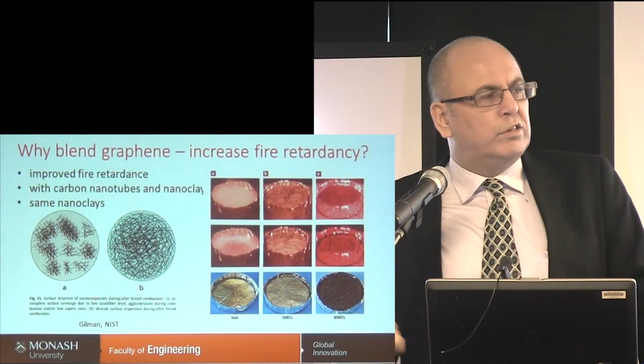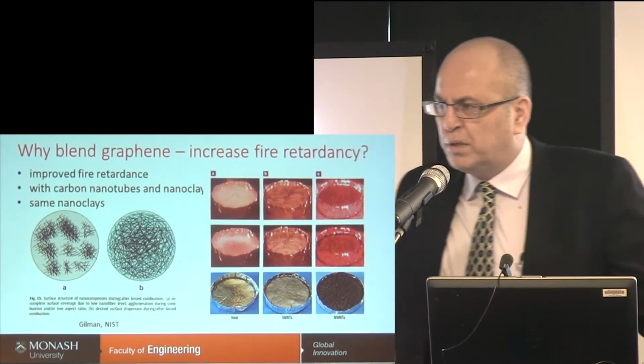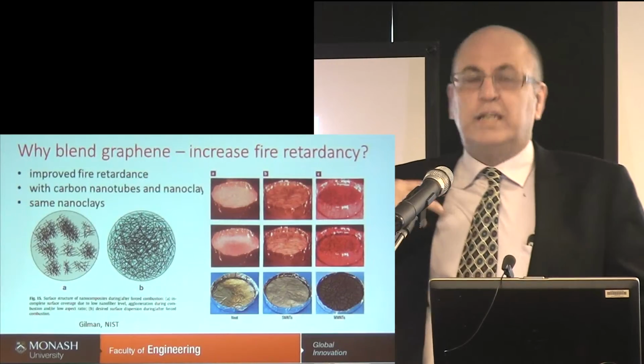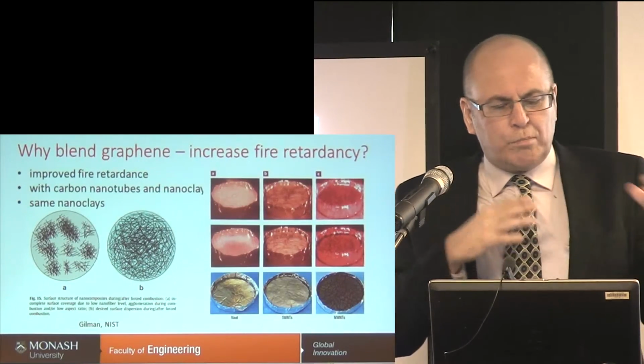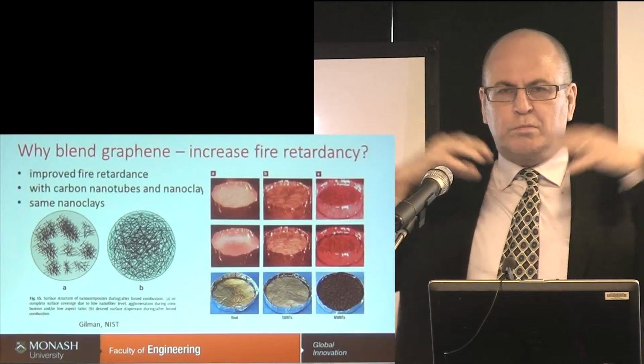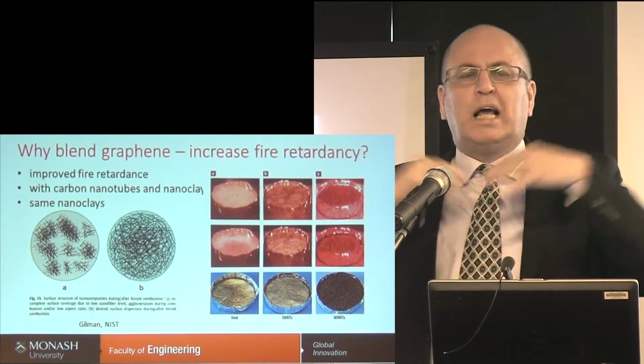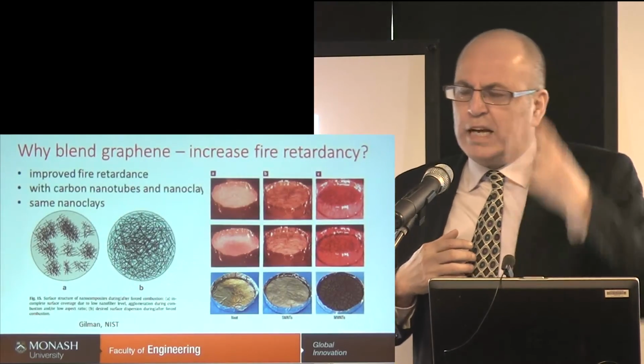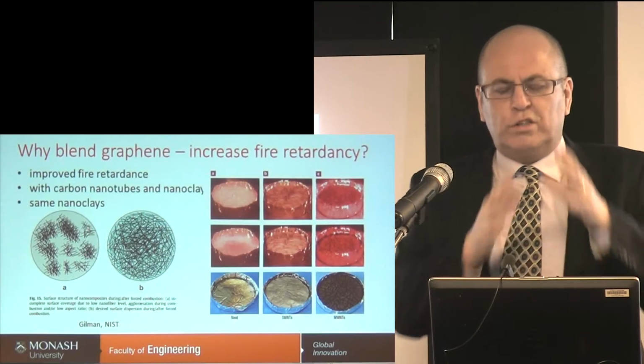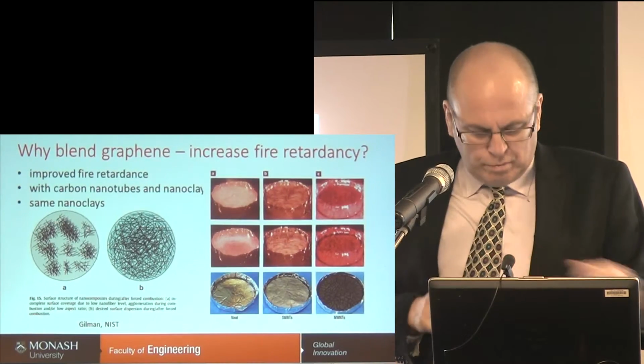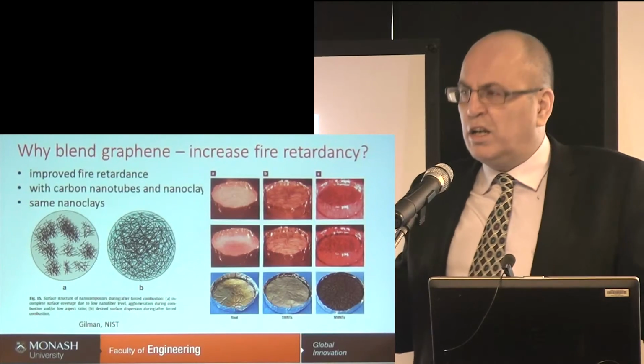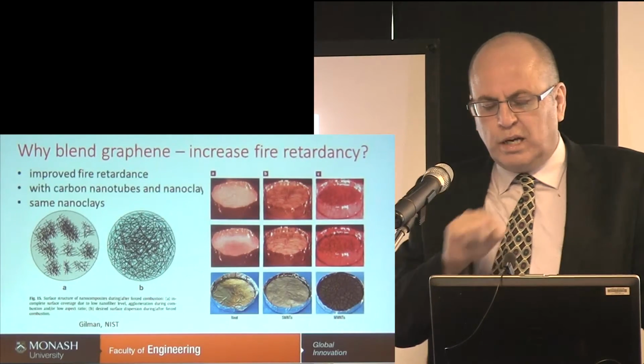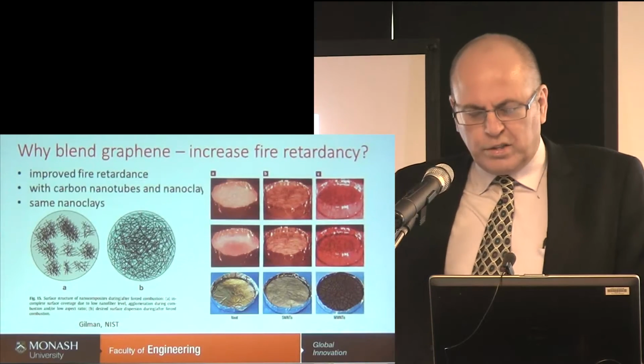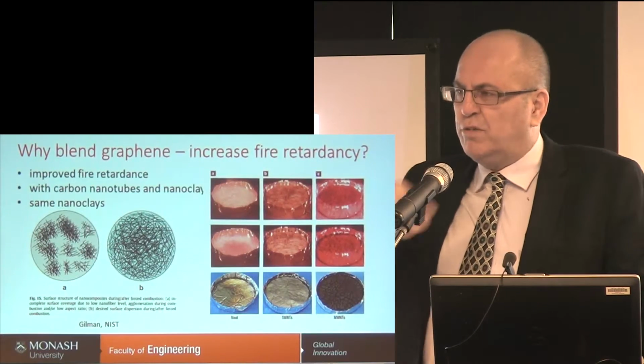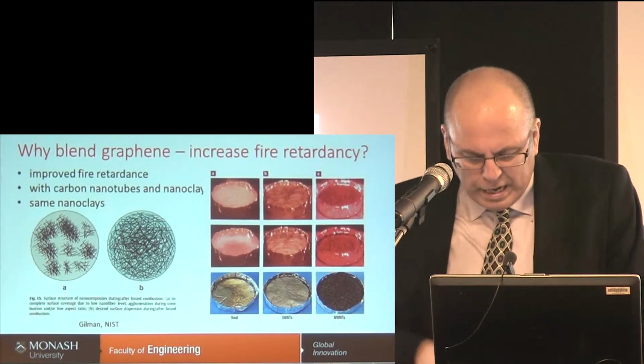Why blend with graphene? What about increased flame retardancy? I haven't really seen this with graphene, but with carbon nanotubes and nanoclays, what you find is that by distributing nanoparticles, as things burn, they tend to move to the top, and they make a layer that reduces the amount of gases that can go in and out and the amount of loss of material. This is actually from people at NIST, where they put nylon with carbon nanotubes, and you can see on the far right that it keeps a char. So if you had maybe a coating on a cable, you could keep that electricity running for a couple of hours.